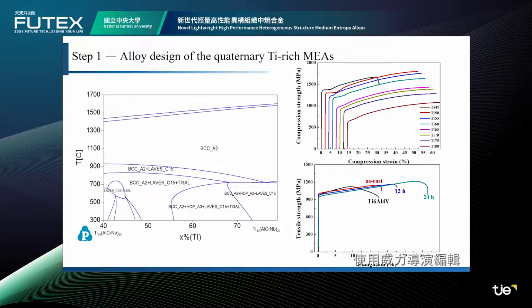It can be found that the microstructure of the alloys can be presented as a single BCC solid solution. Therefore, based on the calculated results, the series of medium entropy alloys from titanium 45 to titanium 80 were investigated. We can find that besides titanium 45, the compressibility of the medium entropy alloys can exceed 50%. In addition, as the titanium content increases, the strength of the medium entropy alloys decreases at the same time.